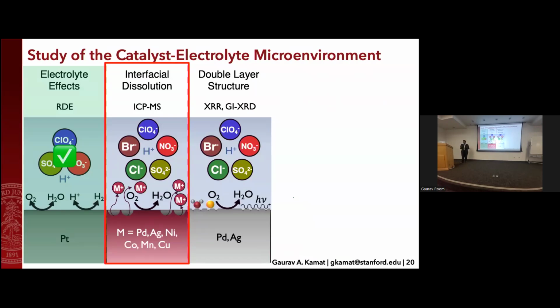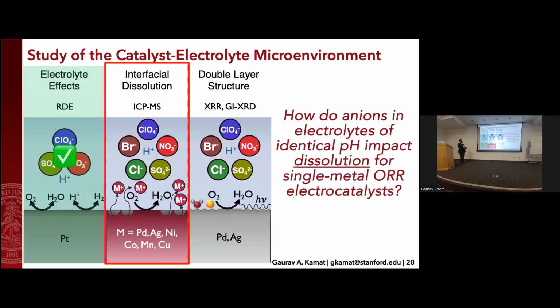So no catalyst will stay active or stable forever. Every catalyst will degrade in some way. The question is how and how fast. And so I looked specifically at how these different anions actually impact dissolution on the surface of metals during oxygen reduction for a number of key interesting oxygen reduction metals that are some of the most studied in terms of being the most active. So how do anions and electrolytes of identical pH impact dissolution for single metal ORR catalysts?